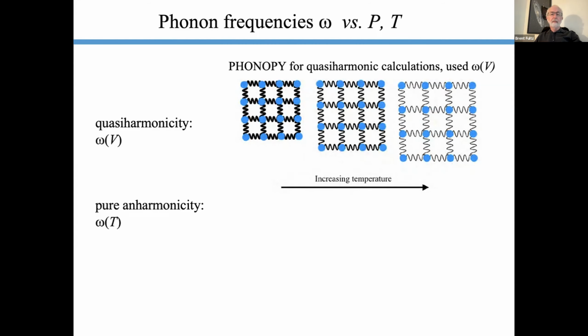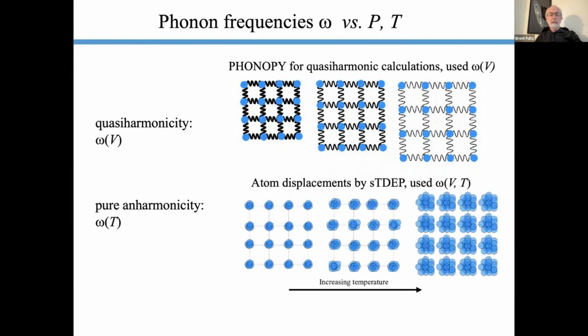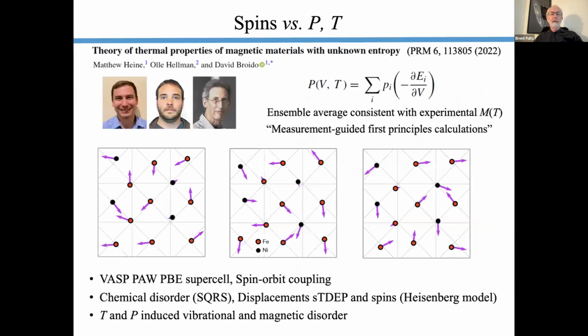It's missing a big piece, and that's that when we go up in temperature, the frequencies change just because the atoms are being displaced. You already have phonons, you have displaced atoms. So the energy cost to add another one is changing. This effect can be as big or bigger than what's expected out of quasi-harmonic theory. So you really have to do both. How do the frequencies change in volume and temperature? So that's just a little background here.